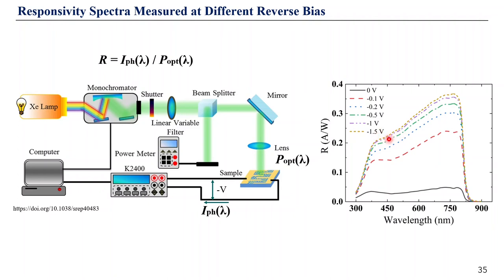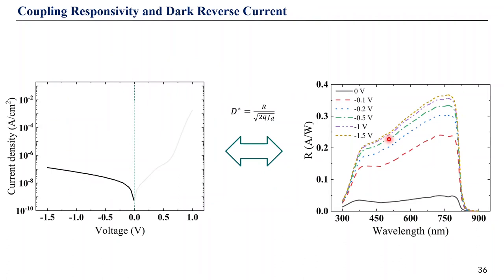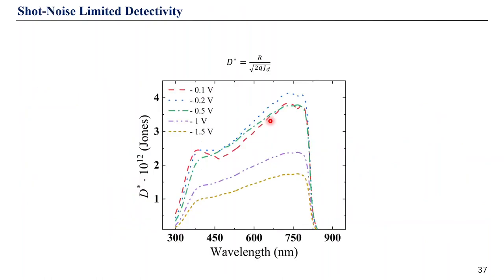However, large bias is not always good, because we need also to remember about the sensitivity of these devices. And in order to quantify that, we need to couple the responsivity spectra with reverse dark current and get the higher estimation of specific detectivity, so-called shot noise limited detectivity, as responsivity divided by square root of dark current at a given bias. And here we indeed see that large reverse bias is not performing the best. The optimized operating condition is at a small reverse bias of 0.2 volts, which results in the highest detectivity. And the value which we get is 4.1 10 to 12 Jones, which is quite high, and later we will compare it with other devices.